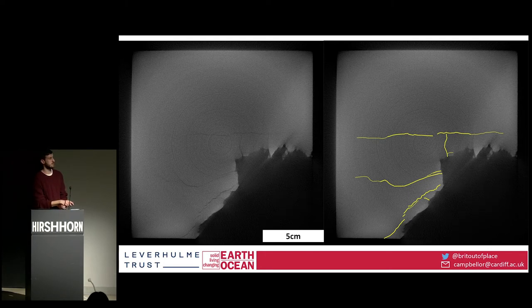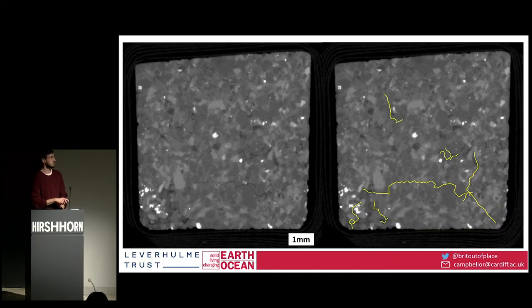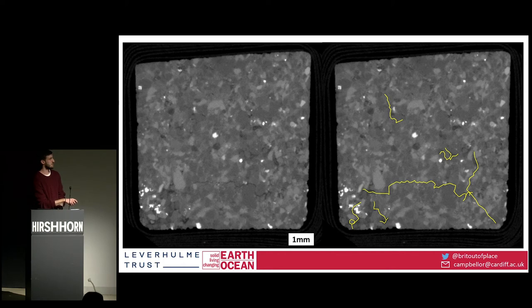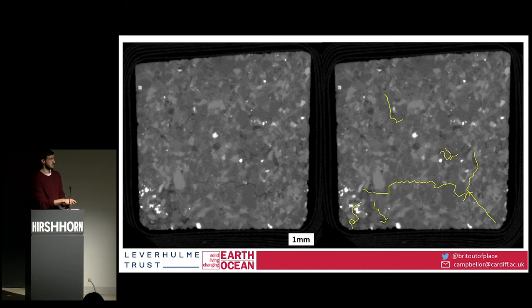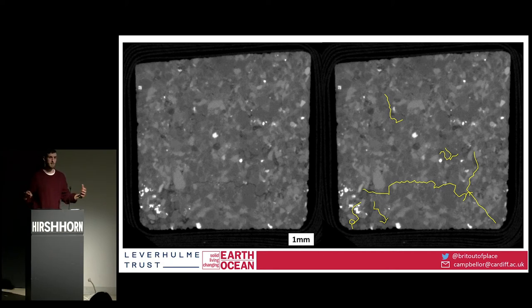So those are the macro fractures — we again see these perpendicular sets. Looking at the micro fractures at a much smaller scale — the whole sample is seven by seven millimeters within a 20 millimeter cuboid — we've got these wiggly fractures that exhibit both transgranular and intergranular behavior. That means we have fractures that go around the grains breaking the grain-matrix boundaries, and fractures that go through the grains themselves. This sample is proximal to our impact, so it's important to understand these behaviors at all scales.